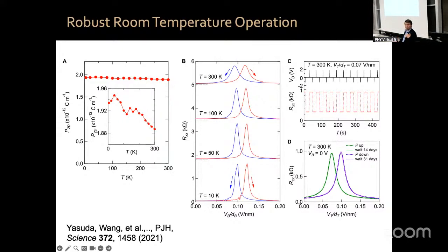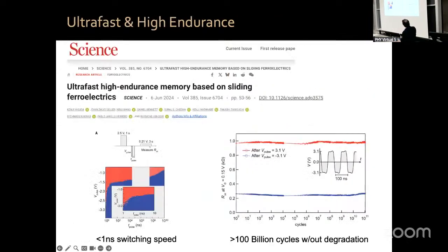We spent a few years looking at how good this could be as a ferroelectric. Just this past year, we published that this turns out to be among the fastest, might be the fastest, and the most endurant ferroelectric in the world. The switching speed is less than a nanosecond. We don't have equipment in my laboratory or in my colleagues' laboratory, I assure you, to actually check how fast it is. We just know it's faster than a nanosecond. That's already commercial grade, and this thing can switch back and forth, back and forth, back and forth.